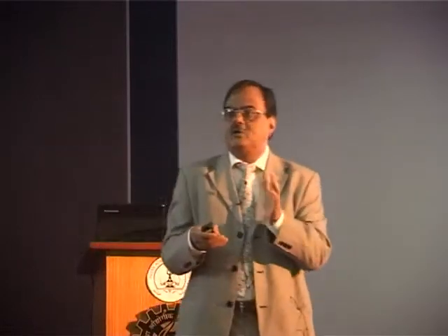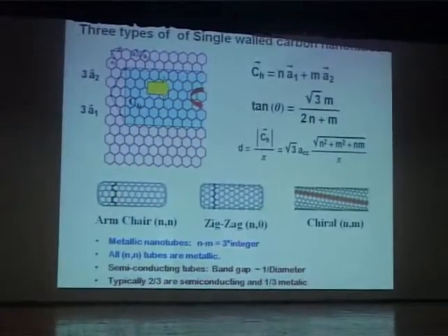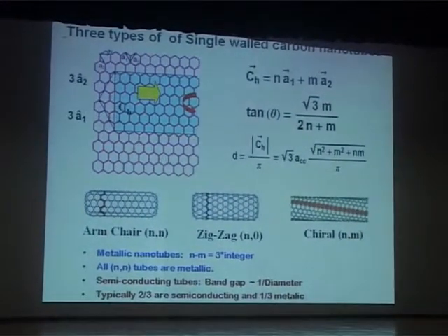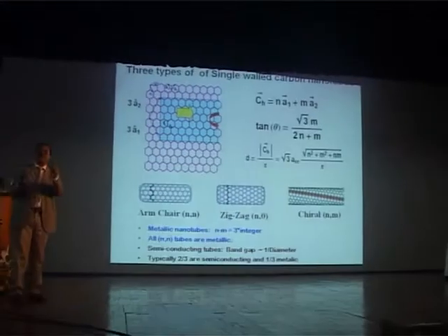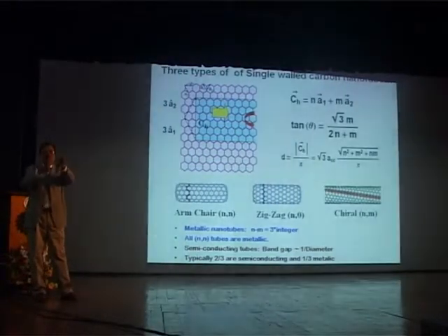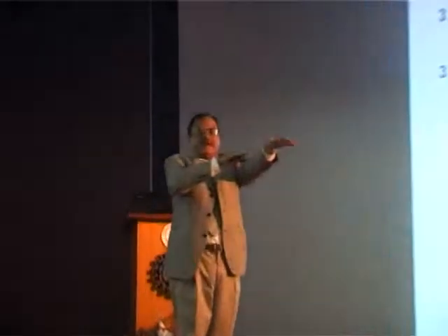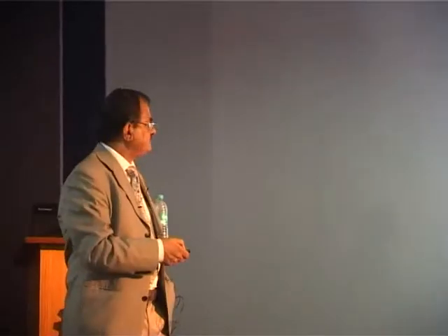So here we have a very interesting thing, that for the same material without any doping, you can have metallic nanotubes and you can have semiconducting nanotubes. And you can easily understand from solid state physics, which I will not do, that if these two integers are such that n minus m is 3 times an integer, it is a metallic tube. So you can have situations, same diameter tube but slightly differently rolled when you make it by different processes, gives you a semiconducting tube or a metallic tube. And when you make them in the lab, 2/3 are semiconducting, 1/3 are metallic.